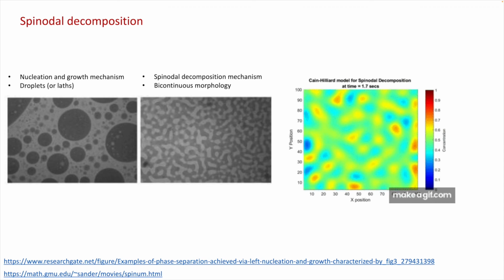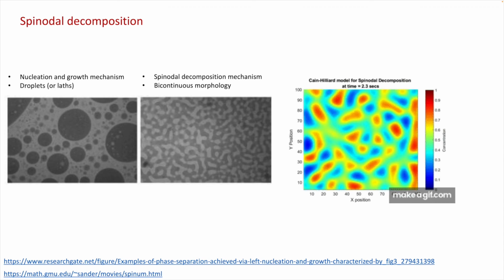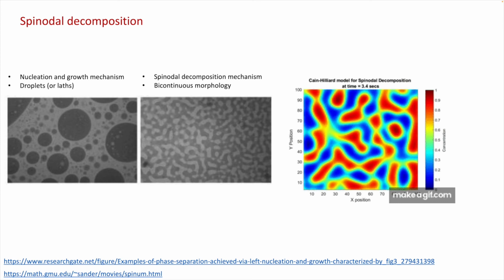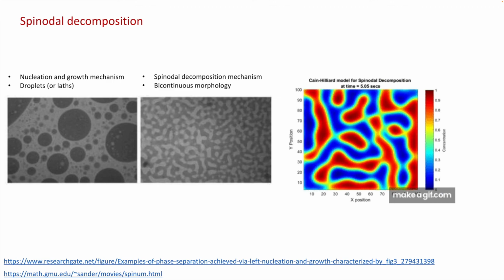First of all, there's no nucleation event. Secondly, the process is spontaneous and happens everywhere in the microstructure. And thirdly, the composition changes over time in each phase. All these features are in contrast to the classical nucleation and growth mechanism.